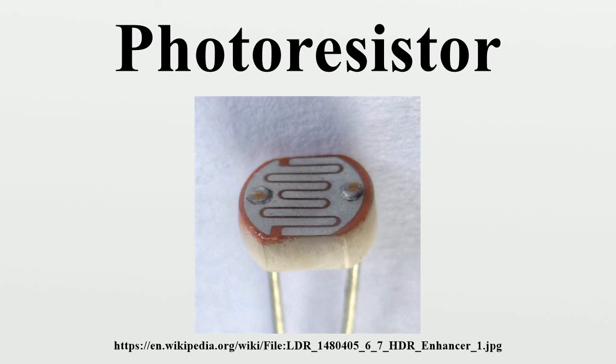The use of CdS and CdSe photoresistors is severely restricted in Europe due to the RoHS ban on cadmium. Lead sulfide and indium antimonide LDRs are used for the mid-infrared spectral region. Ge:Cu photoconductors are among the best far-infrared detectors available, and are used for infrared astronomy and infrared spectroscopy.